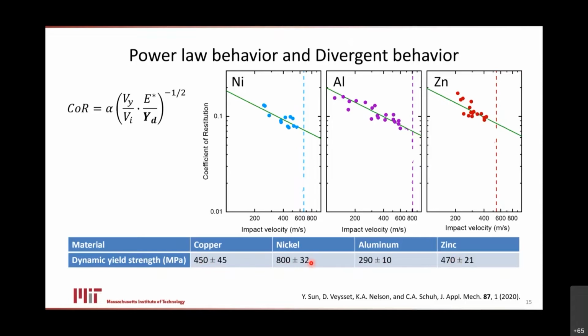So that's useful. The other thing we can do is, now we have an understanding of what plasticity looks like. Plasticity follows a power law. And so when we have an event like bonding, in these cases here, bonding happens at the dashed vertical line. So that bonding event is a departure from classical plasticity. And that is now abundantly clear, because we can now identify points like these where we start to diverge from the power law behavior as we asymptote out into the bonding condition.